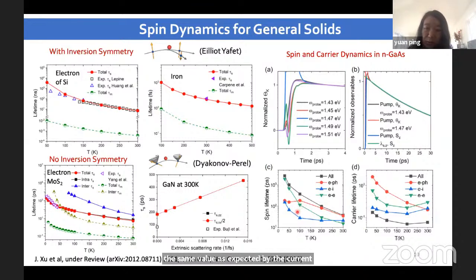measurement. And we can also look at what kind of contribution is the most important. For example, for the spin lifetime, electron-phonon is most important at higher temperature, and electron-electron is more important at lower temperature. And this is very different from the carrier lifetime. For example, the black is also the total, the electron-impurity is important for a wide range until electron-phonon scattering at high temperature becomes most important at 300 K. So this is basically where our theory can tell you what mechanism is important at different conditions, and we can predict reliably the spin and carrier relaxation.